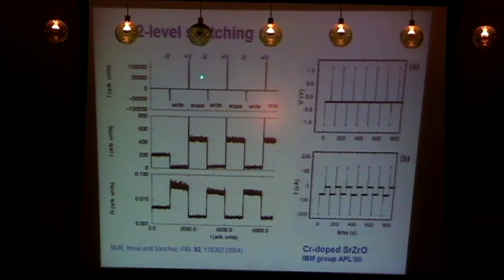The first one is that when you apply a protocol of voltage pulses, positive and negative pulses as a function of time, this is a result of a simulation, you see that the current has spikes that coincide with the voltage pulse application. But when you look in detail at what happens there, you see that after each one of the spikes, up and down, the system commutes between two well-defined values of the current. If you invert the current, you have resistance, and then you see the two values of resistance that the system can be switched in, which is reminiscent of the experiments that I showed a moment before.